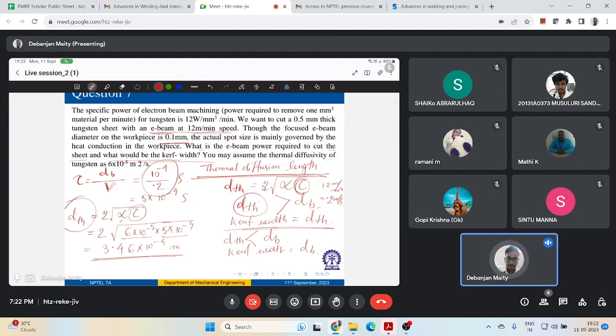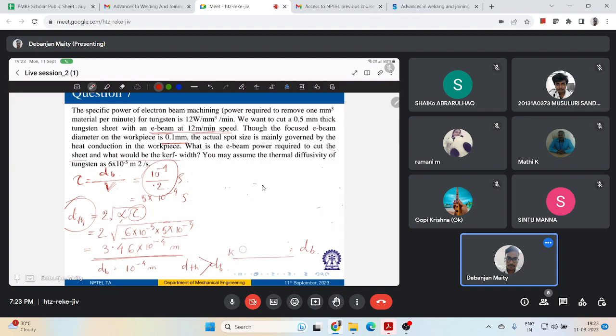So here my thermal diffusion length is coming as something around 3.46 into 10 to the minus 4 meter, and my dB is how much? So it's only 10 to the minus 4 meter, right? So my thermal diffusion length is greater than the E-beam spot diameter. So what about the kerf width then? My kerf width will be the same as the thermal diffusion length.